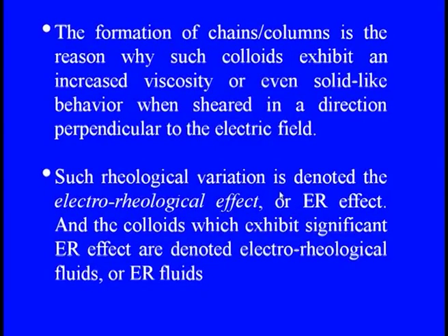So the random dispersion is now characterized by the dipole-dipole interactions, and the string-like features of these particles are decided by the applied field direction. The formation of chains or columns is the reason why such colloids exhibit an increased viscosity, a solid-like behavior when sheared in the direction perpendicular to the electric field.